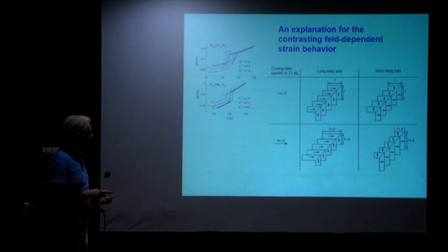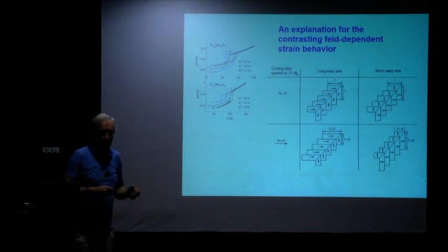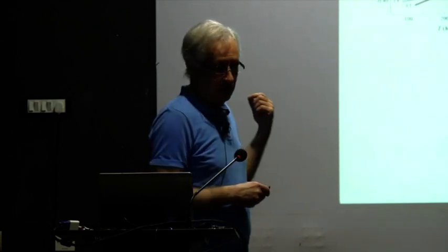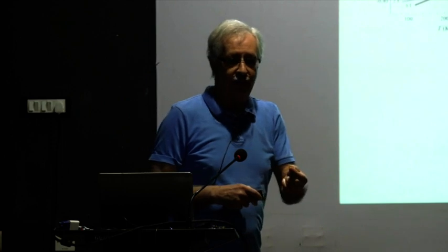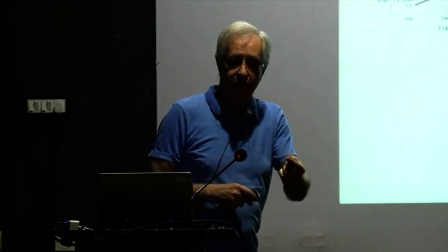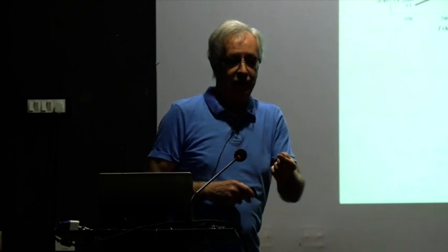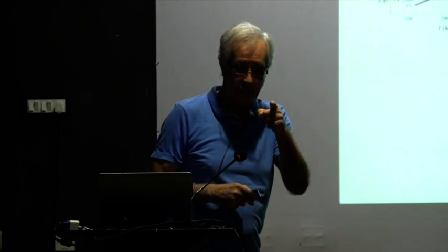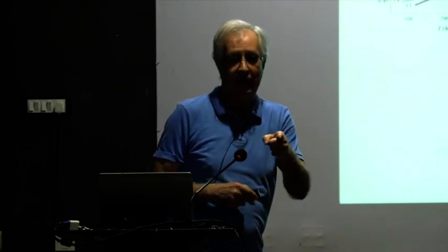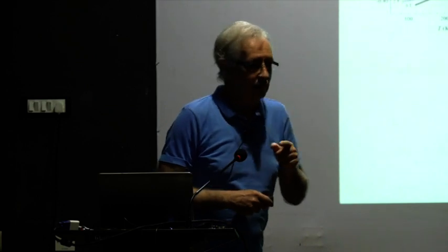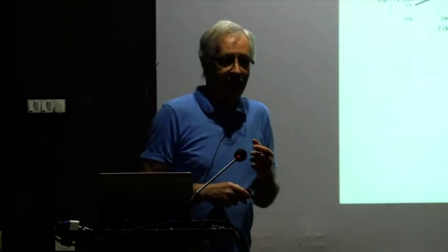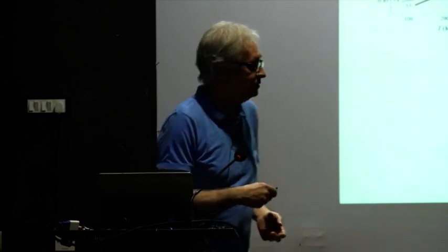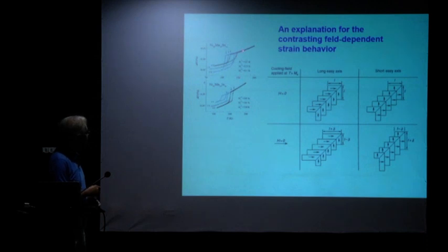Now, if the short axis is an easy axis, then when we cool through the Martensitic transition temperature, if the field is influencing the nucleation process, then it will nucleate martensite variants that have a short axis along the field direction. So as I increase the field, I am making it shorter and shorter, with respect to the initial state.